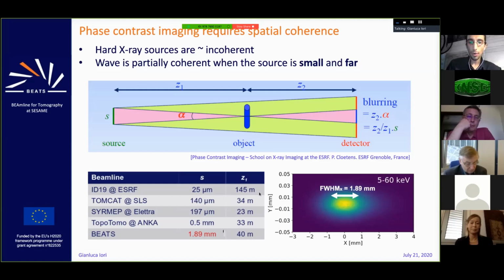And you see how the beamline length can reach 150 meters at high energy facilities like the ESRF. But if we compare BEATS with TOMCAT, SYRMEP, Elettra, and ANKA, we have a reasonable length. We are at 40, we can actually reach 43 meters of propagation from the source to the sample. The physical explanation, again, very simple, is here. A finite source size will project some blurring on the sample, and you can minimize this by taking the object very far away from the source or minimizing the source size.